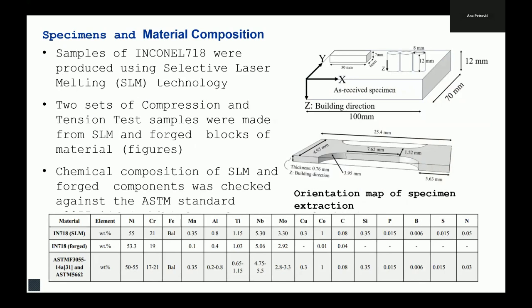There is a composition of the material in the table, and then you can see the samples and the direction of the components that were selected for tensile testing and for compressive testing. And this is the tensile test sample, and the compressive test samples were bars, basically.